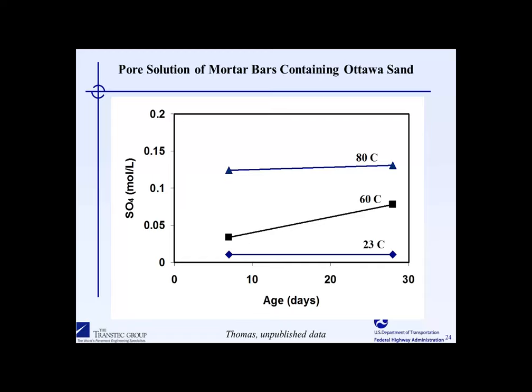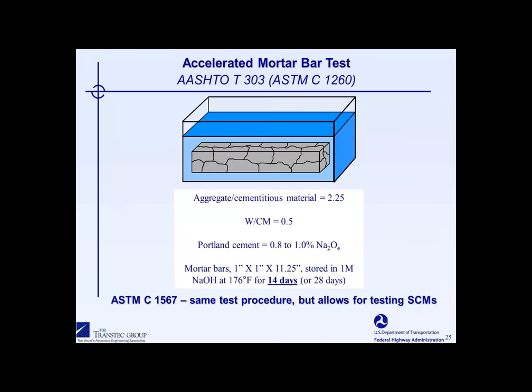So just a word of caution, when trying to accelerate the concrete prism test, it's very, very likely that the expansions will be considerably lower for the reasons that I just discussed. And as of now, neither ASTM nor Canadian standards are considering the accelerated version of this test.